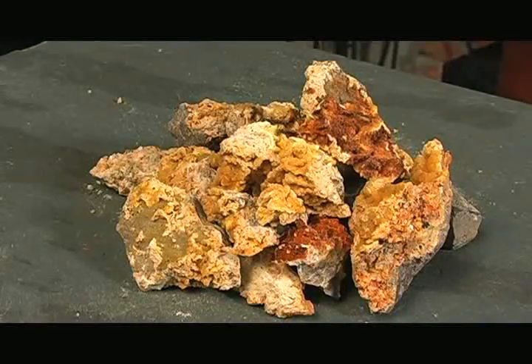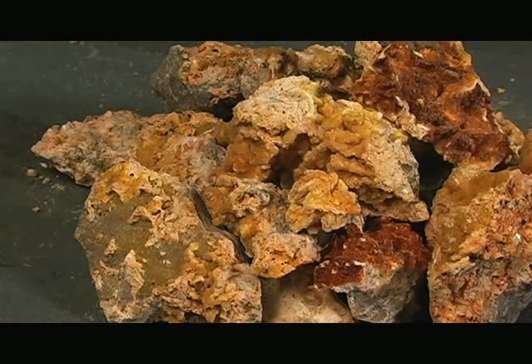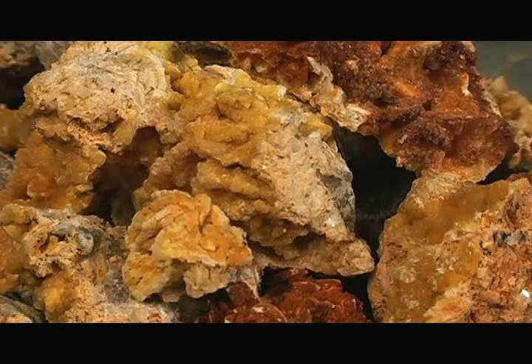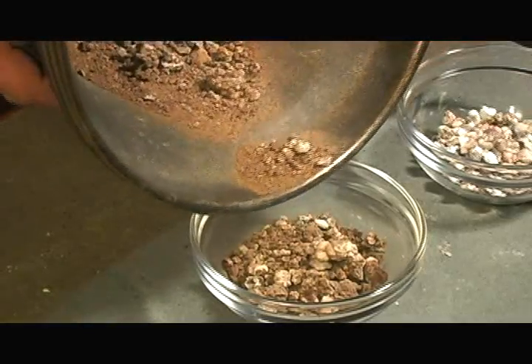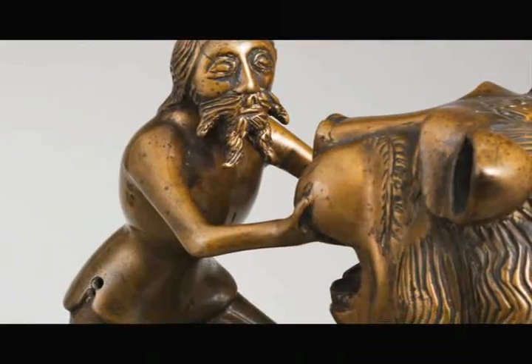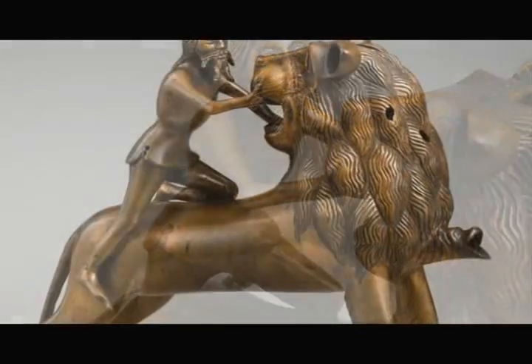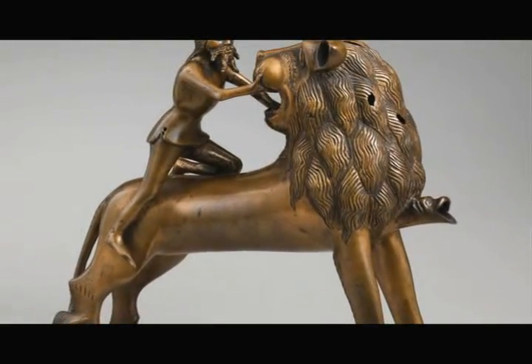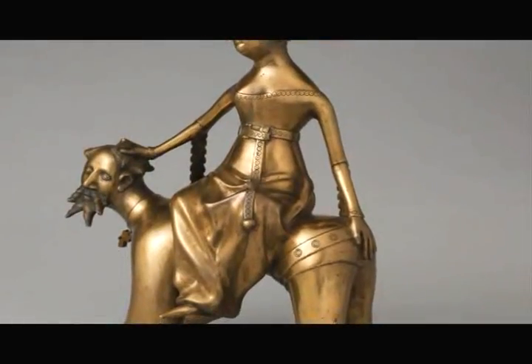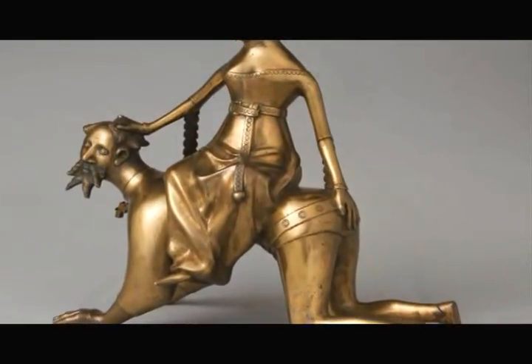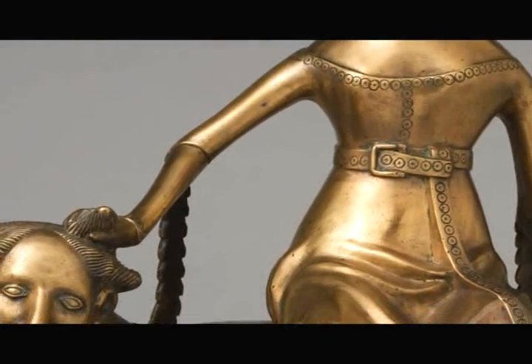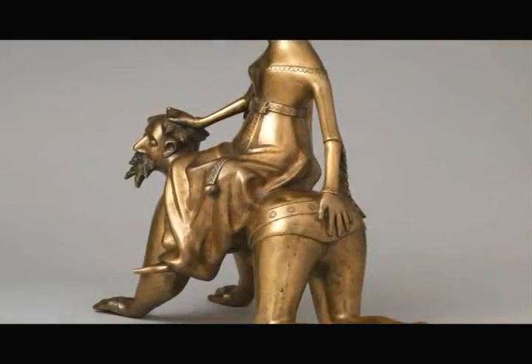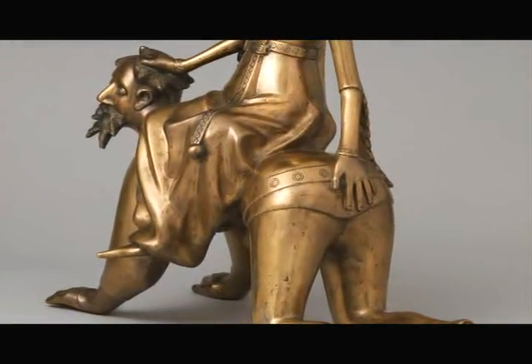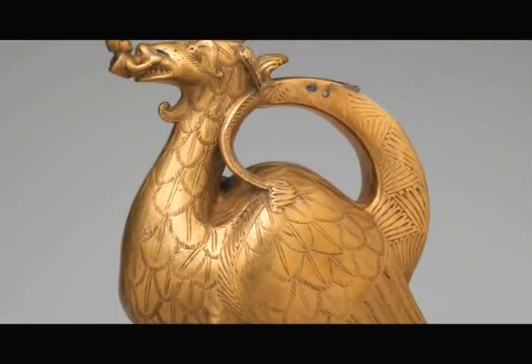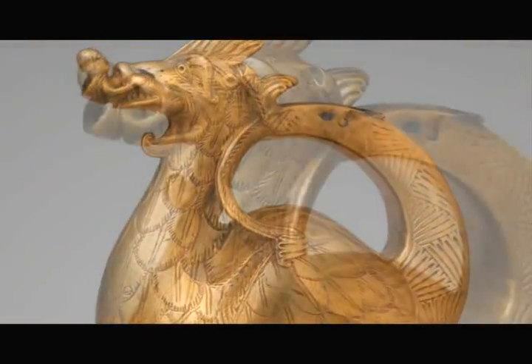There was no recognition that calamine, described by Theophilus as a kind of stone of a yellowish color, sometimes reddish, or tutti, contained zinc, and indeed zinc was not identified as a metal in the West until the 16th century. Its appeal for the metalworker was that it produced an alloy suitable for casting and engraving, and imparted to the copper a yellow color close to gold. As described by Biringuccio, brass is copper given yellow color by art. Surely it was a splendid discovery for which we must thank the alchemists. Geber, perhaps the most renowned of Islamic alchemists, acknowledged the importance of tutti by including it as a component of the philosopher's stone.